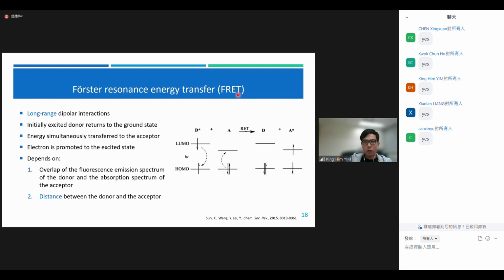So another mechanism, we call it FRET. FRET stands for Förster resonance energy transfer. It is a long-range dipole interaction. On the right-hand side shows the mechanism of this FRET. The electron can be first promoted to the LUMO, and then upon the relaxation of this electron back to the HOMO, the energy will be transferred simultaneously to the acceptor. And then in the acceptor, an electron from the HOMO can be promoted to the LUMO.